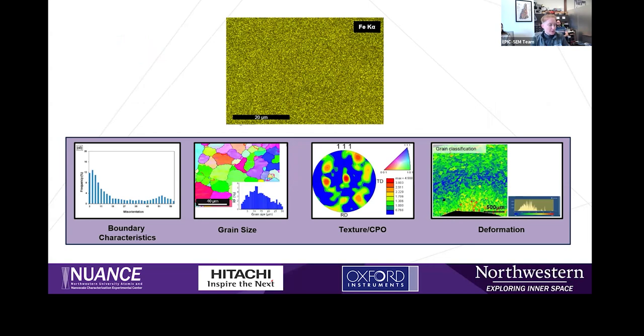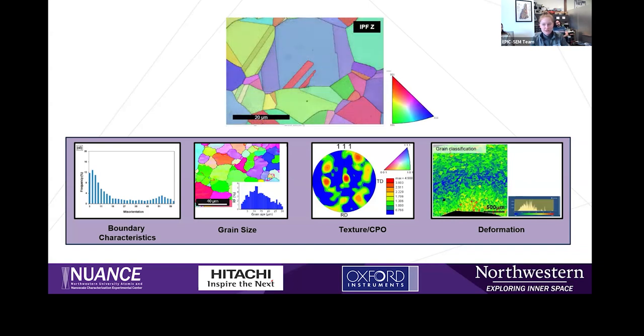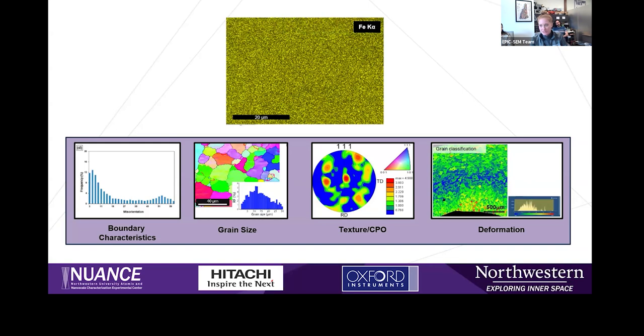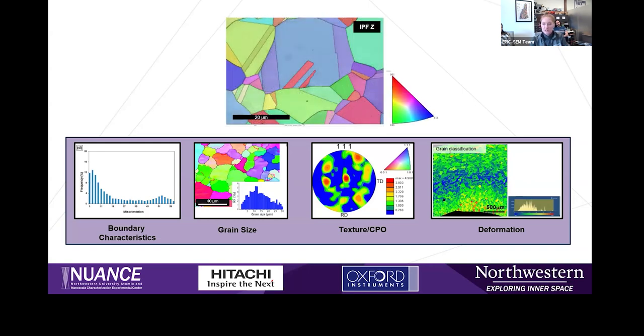If you're not familiar with EBSD, or electron backscatter diffraction, it is used similar to EDS, where you can get spatial information on the composition of your sample, but with EBSD you get spatial information on the crystallography of your sample. So this is a steel sample. If you're just looking at the iron EDS map, you don't see the grains, but when you do EBSD, you can see the grains, you can see some of the twins. And this information is very useful to characterize things like grain boundary characteristics, grain size. You can look at textures or crystallographic preferred orientations or deformation, so strain in the sample or in the crystal.